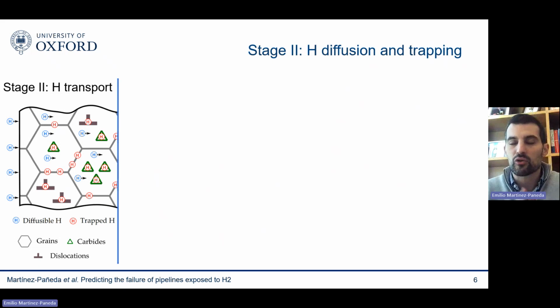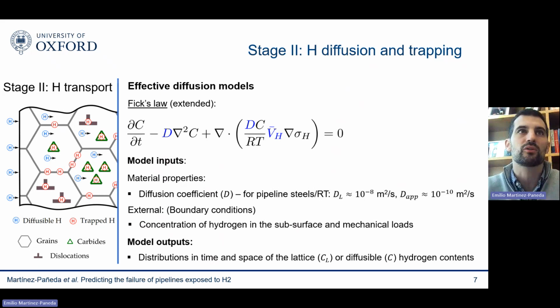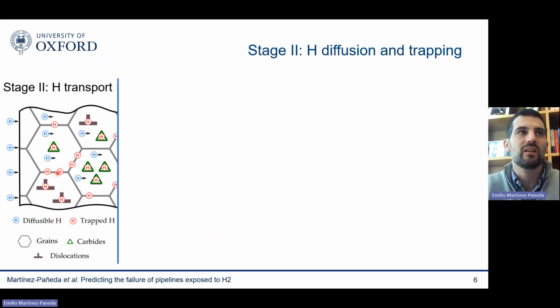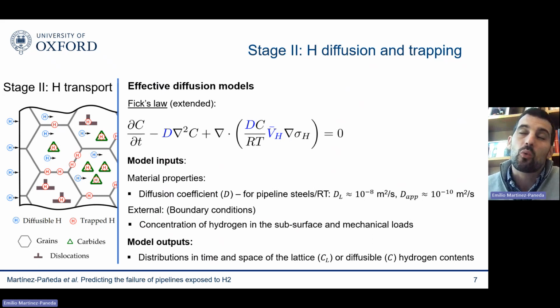Okay, so once you know how much hydrogen is coming into your metal, then you need to quantify the distribution of hydrogen within the pipeline, within your component, and also within your microstructure. Because hydrogen not only travels freely through the crystal lattice, as you can see here, but it's also trapped, sequestered at microstructural defects such as grain boundaries, dislocations, and carbides. So there's a couple of ways of doing this. First, one approach is to use effective diffusion models, which are based on an extended version of Fick's law. You can see here the concentration of hydrogen is driven by gradients of concentration and also by gradients of hydrostatic stress, again, a strong coupling with the mechanics part.